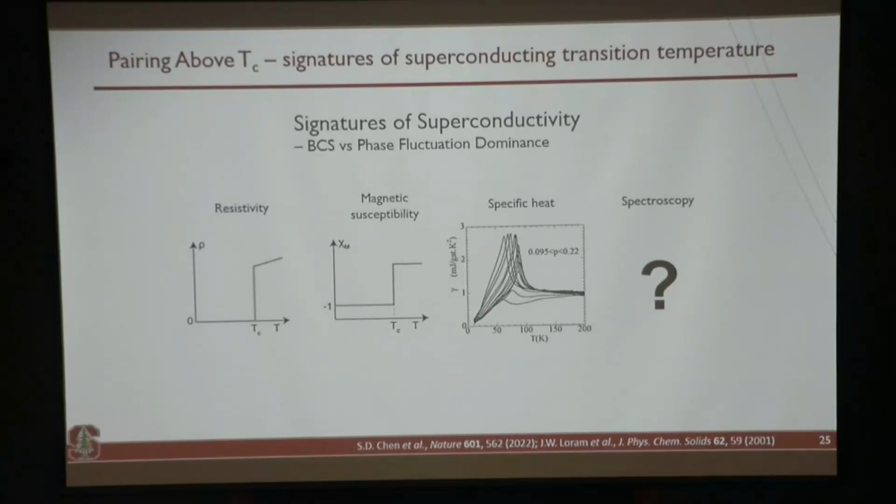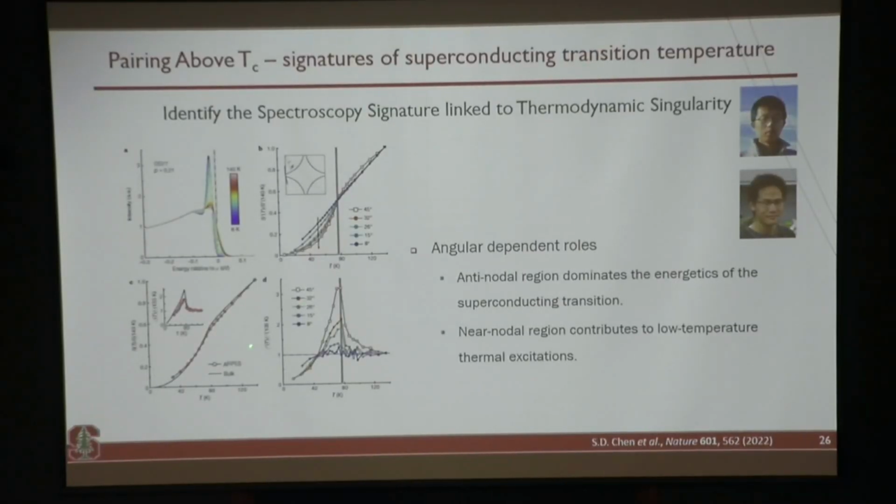For people who are familiar with photoemission or STM or this kind of spectroscopy, temperature-dependent experiments are very, very hard for precision measurement. And this being overcome, what Schulte and Makoto have found is that if I use, instead of density of states, just the spectral weight at the chemical potential, and use the standard way to calculate the entropy of the system as a function of temperature, then you get an entropy curve that looks like this.